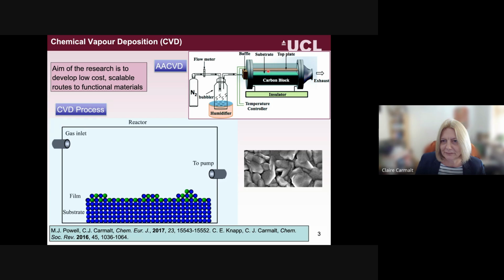So the other advantages of the AACVD process, as well as overcoming the volatility of the precursors, is that it can lead to the formation of very highly textured surfaces. And this just shows you an SEM of one coating that we have produced using AACVD. And by forming highly textured surfaces, you can then tune it towards the functional property that you're interested in. It also is compatible with scaling up to the industrial online APCVD process, but I'll come back to that later on in my talk.